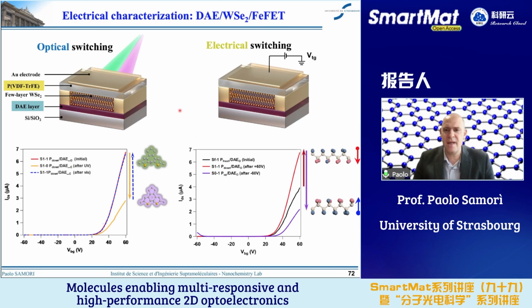We start with the tungsten diselenide that is actually in the P down state, that is the one with the higher current, and that is obtained by applying a voltage of plus 60 volt. Then when we apply a negative voltage, we can bring all the dipoles into the P up state, and in the P up state the electron current is decreased by about 68%. And when we then bring it back to the P down state by applying a plus 60 volt, we can recuperate fully the higher current through the junction. So this proves the electrical switching capacity of the device.